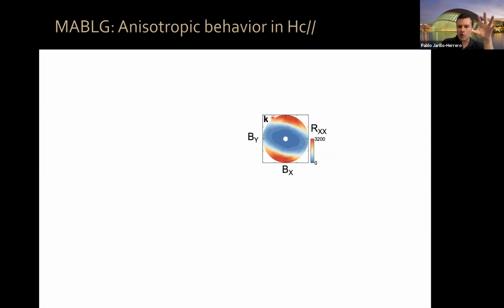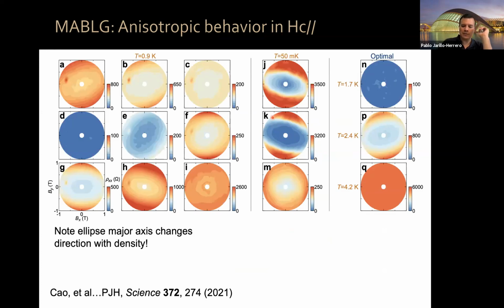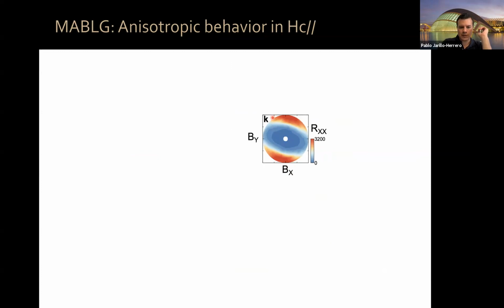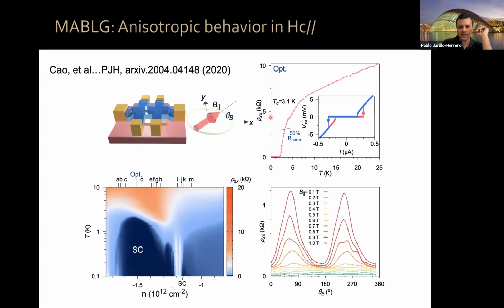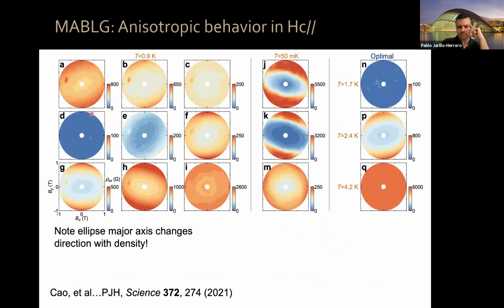Now what we can do is look at all of this as a function of doping. So if we go to the superconducting dome, we have here different points, marked by these letters, and then we can go here, and this is how the anisotropy evolves as a function of doping. This is at base temperature. In some regions, this is at optimal doping. Turns out in our setup, we have a maximum 1 Tesla in-plane field. So at optimal doping, for example below 1.7 Kelvin, we cannot detect any anisotropy because the critical field is too high in all directions. But if we increase the temperature, we can see the appearance of an ellipse, which then disappears in the normal state. At this intermediate temperature of 0.9 Kelvin, we can look at the evolution of the ellipse with density, with doping.